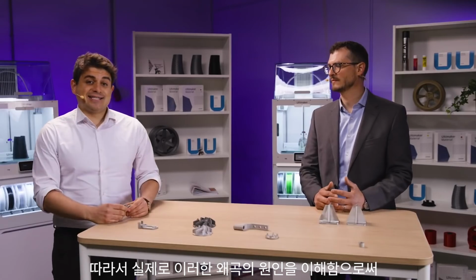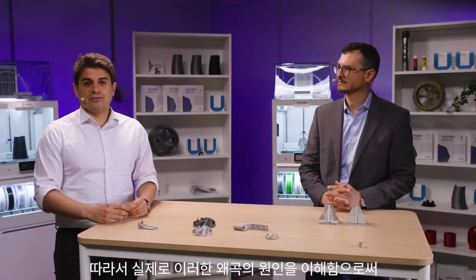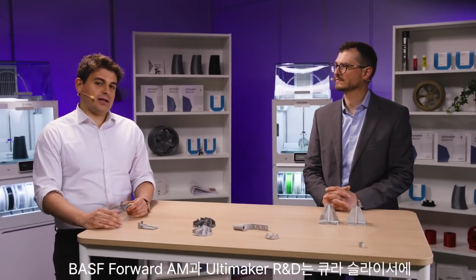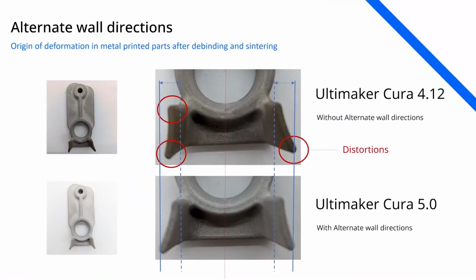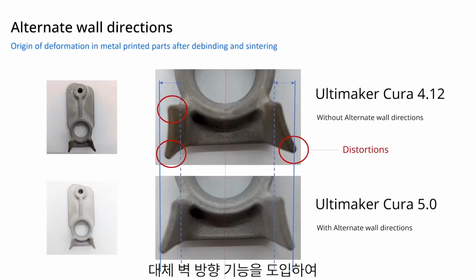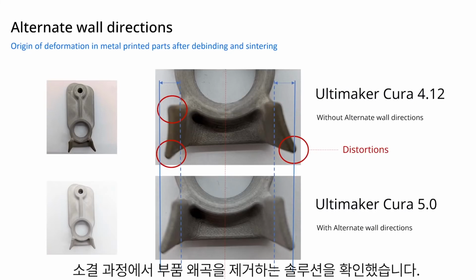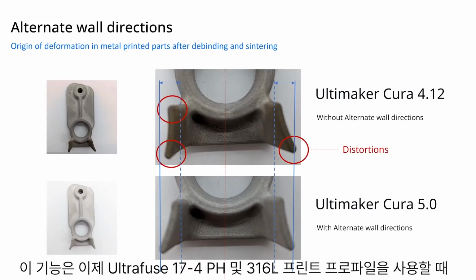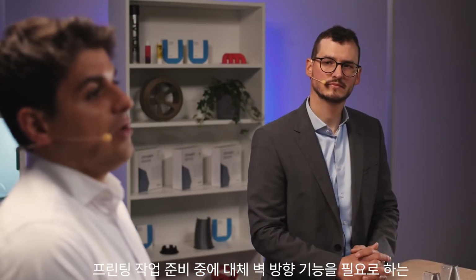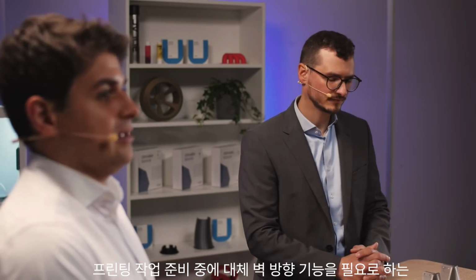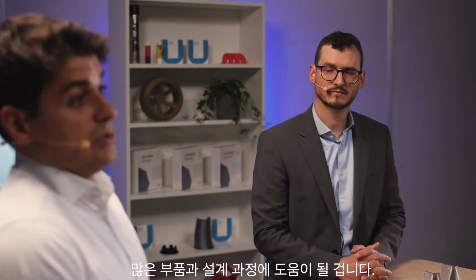So by understanding the origin of this distortion, BASF Forward AM and Ultimaker R&D identified, in the introduction of the alternate wall directions feature in the Cura slicer, a solution to remove part distortions during the sintering process. This feature is now present and used as default setting in the new Cura 5.0 when using both UltraFuse 17-4PH and 316L print profiles, given its key role and the high number of parts and designs that require the alternated wall direction during print job preparation.